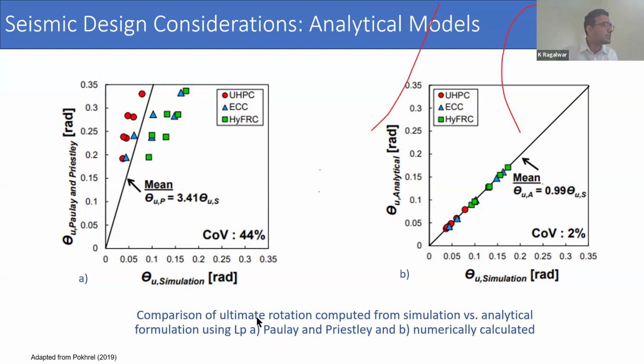So this plot shows a comparison of ultimate rotation computed from simulation versus the analytical formulation of plastic hinge length. Plot A shows the simulated rotation versus the rotation calculated by Paulay and Priestley, who came up with an analytical model for conventional concrete. Ideally, if the model matches the simulation, the plot should have a 45 degree fit, such as shown in plot B here. That means these models are not good enough, or they do not capture the plastic behavior or the capacity of materials like UHPC.